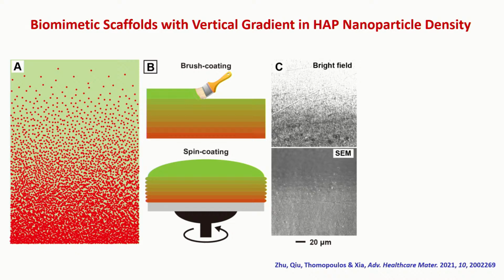And this, of course, you would argue is not a highly reproducible method. Brush coating, after all, depends on the pressure you apply and the amount of liquid you apply, so eventually the thickness of the film may not be so well controlled. So that's why recently we switched to spin coating. That's really the most widely used technique in a microfabrication lab, right, to make very thin polymeric films. But in this case, we are using a mixture of hydroxyapatite and this polymer solution, and you can do spin coating layer by layer again. Okay, so from bottom to top, the concentration of the mineral phase is going to decrease, and in this way, we can easily control the thickness, and we can have a very robust method to control both the composition and the thickness of this.